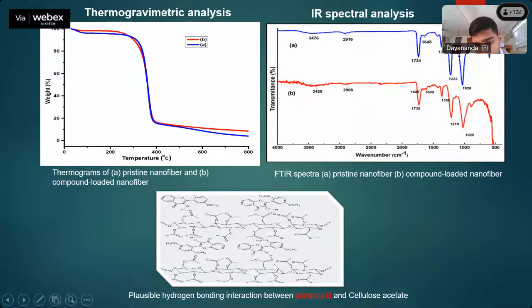So it was anticipated that there is a hydrogen bonding interaction between the loaded compound and the cellulose acetate. Mechanical properties were also analyzed, and it was found that the mechanical property was increased while elongation at break decreased, mainly due to the improvement in the crystalline nature.